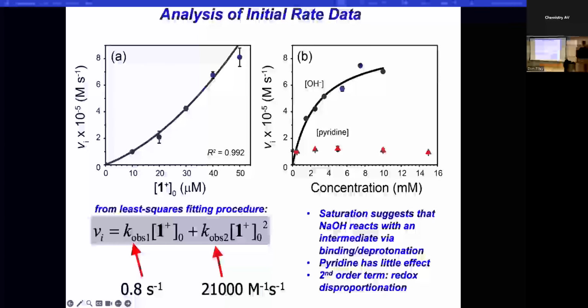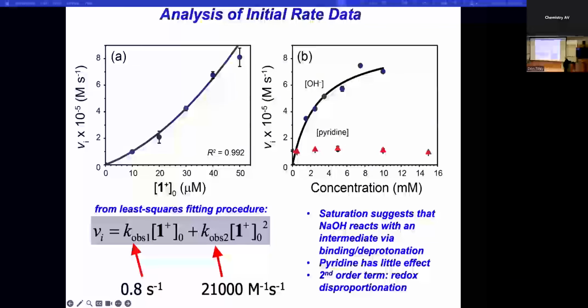And here is that kinetic data reduced by a least squares fitting procedure into a rate equation. And this shows the data. But one of the things that jumps out at you immediately is this second order term in the oxidized cube. So this indicates that somehow two of these cubes have to come together to make oxygen. We spent a lot of time thinking about that. But there's also this first order term, and we now believe, and I'll elaborate on this in a little bit, that this term actually has to do with the initial reaction with hydroxide.